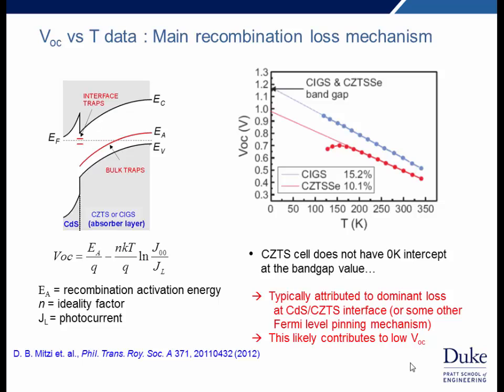It means we're getting recombination in the bulk of the material. In the case of CZTS, which actually has the same band gap, you could see this extrapolating well below the band gap value. And this is typically taken to be attributed to a dominant recombination loss at the absorber-buffer interface. And this is not something you'd like to see. But it's important to point out that this can be due to other Fermi level pinning mechanisms as well. In either case, this is likely to be indicative or contributing to the low VOC at room temperature as well.